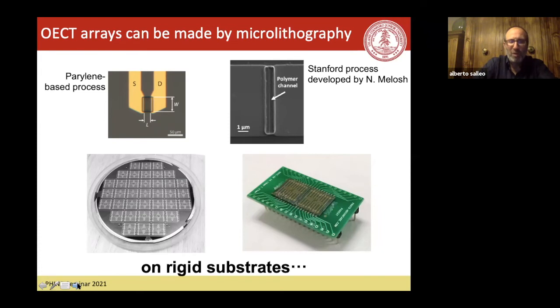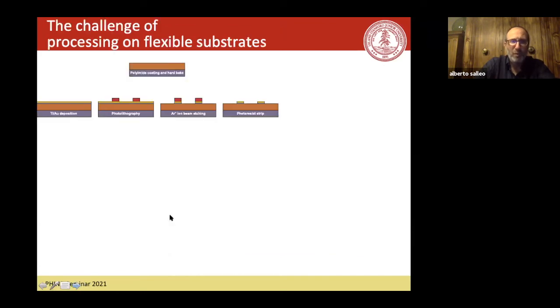So this is a process we developed for rigid substrates, but I told you that we're interested in wearables, and of course, rigid substrates are really not ideal for wearable technologies. So we wanted to develop a similar process that would work on flexible substrates. And so the idea is you have your substrate, and then you coat it with polyimide, which you can spin coat, and you deposit everything on it, and then eventually, for example, your metal. So here is your metal layer. Then you put your photoresist, you define your photoresist, you etch down, you strip the photoresist, and now you have your metal traces.